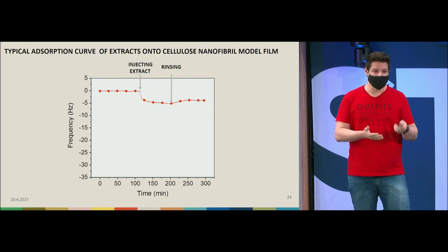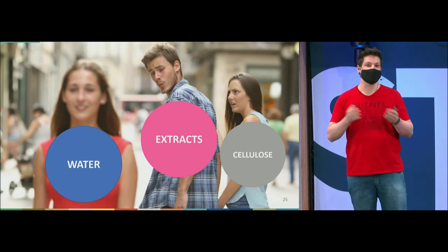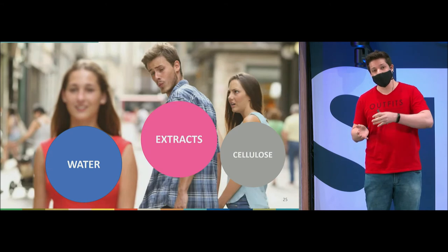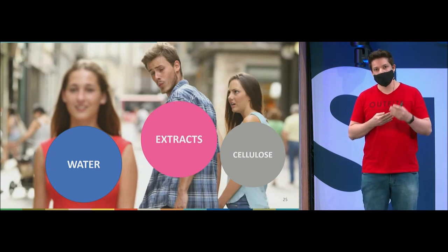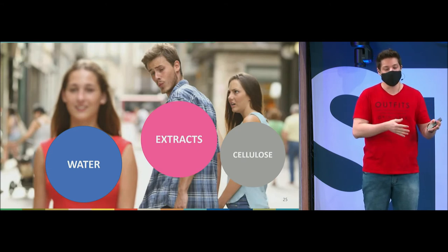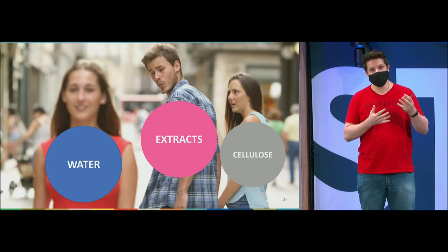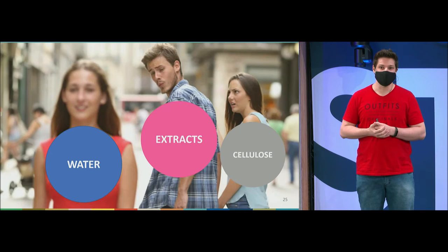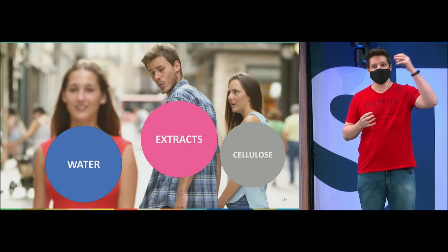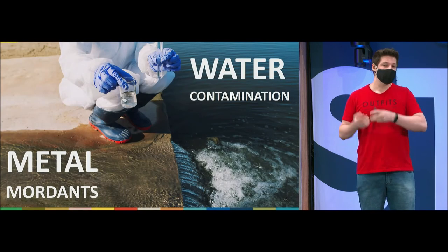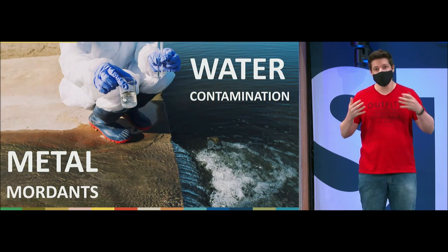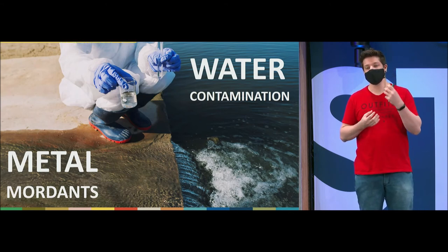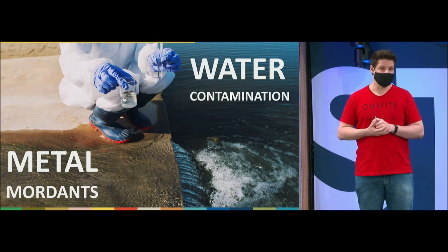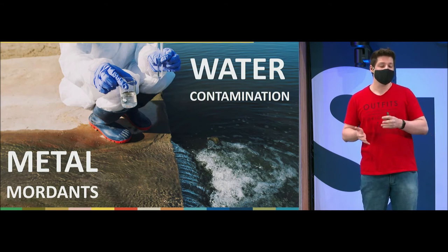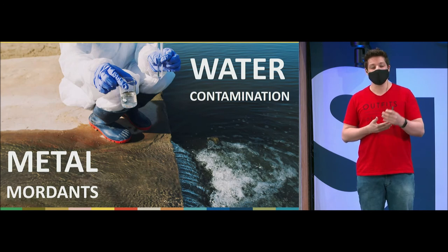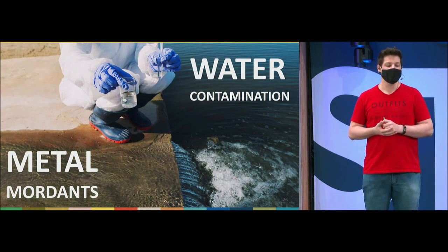And what we have learned from these initial results is that the extracts are attracted by the cellulose, but not that much, because we have water involved, and here probably the forces involved are hydrogen bonding. When you have a lot of water in your system, you are competing with water, and it's difficult to coordinate the binding between the dyes and the textile. So what they usually do in industry is use substances to improve this interaction, materials that have stronger forces involved, like electrostatic charges. And for this, they go for metal. But the problem with the metal salts is that you have contamination of water. So this is one of the major problems in the dye industry.